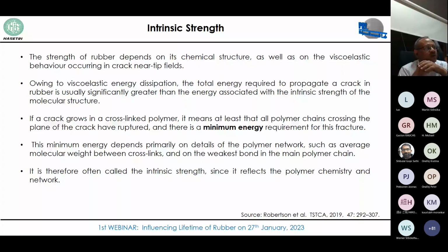And if you see the complete crack growth curve starting from the threshold level to the ultimate strength or critical tearing energy, this is very clear. So that's the reason the synthetic rubbers actually derive their strength from this viscoelastic energy dissipation. And therefore, the total energy required to propagate a crack in rubber is usually significantly greater than the energy associated with the intrinsic strength of the molecular structure.